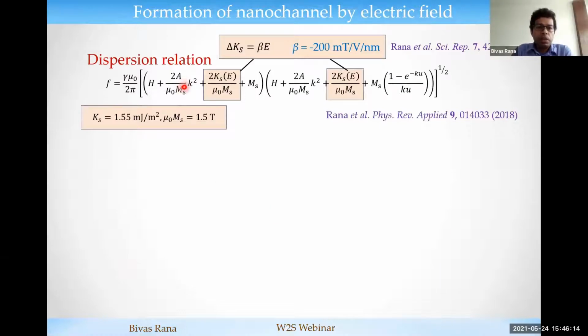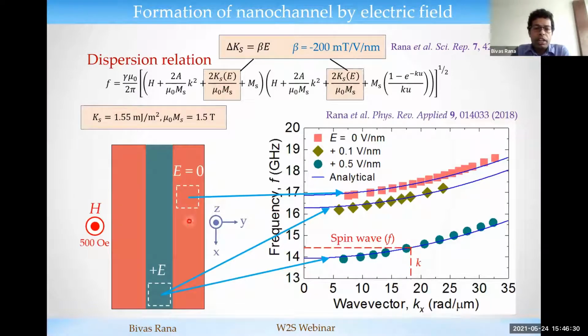If you see the dispersion relation of the spin wave in this system, where the spins are aligned in the out-of-plane direction, the frequency can be written as a function of perpendicular anisotropy. So we are tuning this perpendicular anisotropy, and let's say you draw how the frequency varies as a function of k vector. Outside of this channel, where you are not applying any gate voltage, this is the dispersion relation, and inside the channel the dispersion relation is downshifted because we are applying the gate voltage and we reduce the perpendicular magnetic anisotropy. So if you want to excite the spin wave, for example at 14.4 gigahertz frequency, you can only excite the spin wave inside this channel, because outside of this channel it is prohibited, and that is the way you can confine the spin wave.